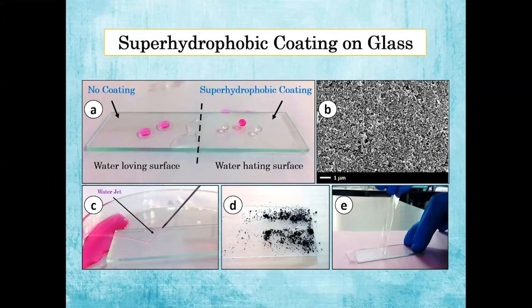We have not gone through the nano indentation or sandpaper abrasion test, but these stability tests we have tried. In image D, you can see the self-cleaning effect, where carbon nanoparticles are spread on the superhydrophobic coating, and the water drop takes away the dust particles. So this is the primary result. And this coating methodology was tried on different substrates.